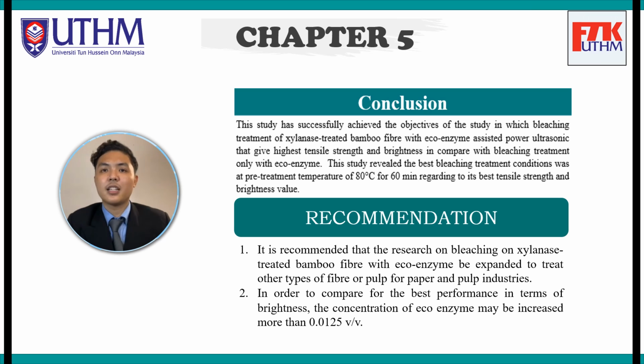According to the results obtained, XYLANASE-treated bamboo fiber with ECO-ENZYME assisted power ultrasonic gives the best tensile strength of 553.44 MPa with brightness of 72.25 at 80 degrees Celsius for 60 minutes. Nevertheless, the highest brightness obtained is 73.66 with a low tensile strength of 173.54 MPa at a temperature of 80 degrees Celsius for 120 minutes with low concentration of ECO-ENZYME, compared to treatment with only ECO-ENZYME. The best bleaching treatment condition was at pre-treatment temperature of 80 degrees Celsius for 60 minutes, given its best tensile strength of 553.44 MPa and brightness value of 72.25.